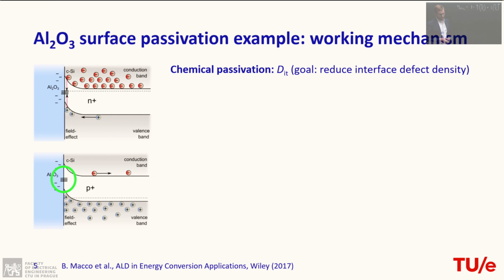So how does this work actually? You have some defects that are present in the bandgap of your crystalline silicon over here, as characterized by these lines. So you want to reduce that density, and the way to do this is to basically bring new elements there. There's also the aluminum oxide and also hydrogen, which is in this material. And in this way, you can reduce this so-called DIT, or the interface defect density. And this is the chemical passivation.